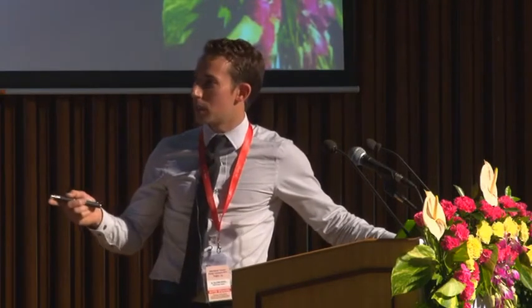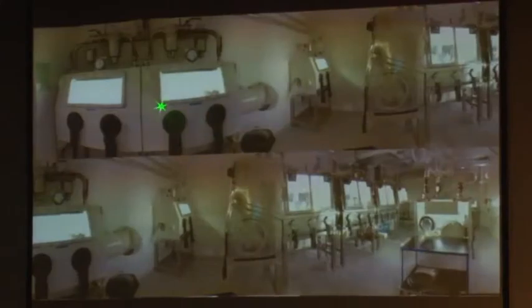First of all, the first box here is a powder accepting box, and the plutonium or the thorium or whatever gets unpackaged in here, and then we have a powder milling box, a powder or pellet pressing box, a quality control box, and a sintering box right here. After the pellets have been created, they are extracted and taken to one of these 3 boxes where we can either drill holes in them or grind them to appropriate size, and then they are transferred over here to this box where they're inserted into claddings and welded shut.